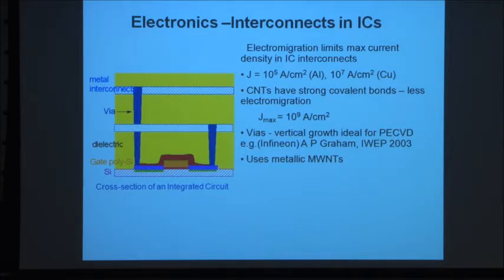Okay, the last 5 minutes or so. One of the other potential applications for CNTs is to replace copper. As densities and sizes of devices go smaller and smaller, we have to get a replacement for the copper via interconnect. So, you know, our CNT is good for that. Well, if you look at the current density of aluminium, it's about 10 to the 5. For copper, it's 10 to the 7. CNTs, in theory, have about 10 to the 9 amps per centimeter squared. So in theory, they should be much, much better than copper for vias and interconnects.